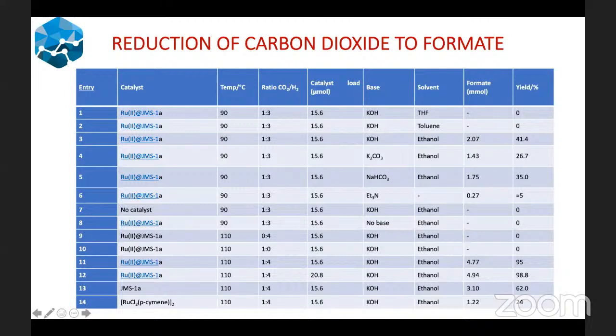We also looked at the effect of the ruthenium p-cymene complex, and we realized that the ruthenium p-cymene complex is also able to catalyze the hydrogenation of carbon dioxide to formate, of course with a very low yield of 24%, because this is a dimer. You know, with the dimers, they're not very active towards hydrogenation of CO2 to formate. So these are the results that we obtained.